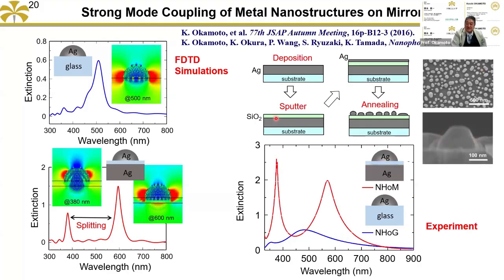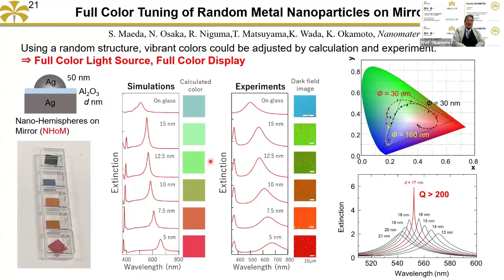But the resonance peak is split into two, and it is very big and very sharp. So we can control the intensity and the sharpness of the resonance peak by using this structure. We call it the nanohemisphere on mirror structure, the NHOM structure. The most important advantage of this method is you don't have to care about the nanostructure. In many cases, you have to fabricate a very fine structure by e-beam lithography, but in this structure, just a random particle is good enough. But you have to control the thickness. Then you can obtain all the RGB full colors.